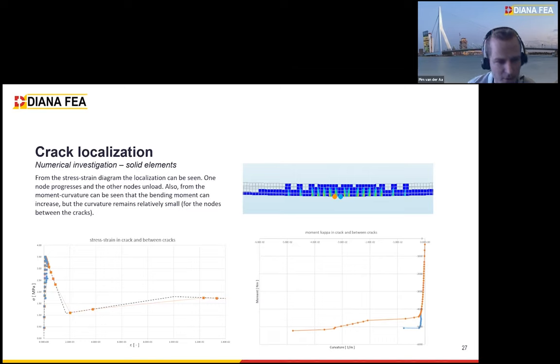And on the left side, you can see that indeed the blue line is actually the micro cracking, where you see the unloading at some point of the cracks. Also on the left side, you can see that all the points are nicely respecting the stress strain diagram, which was used as input.